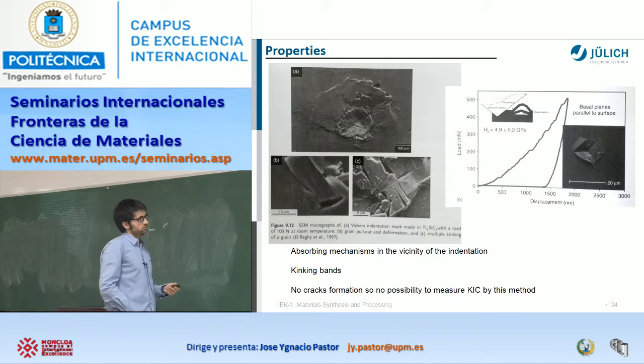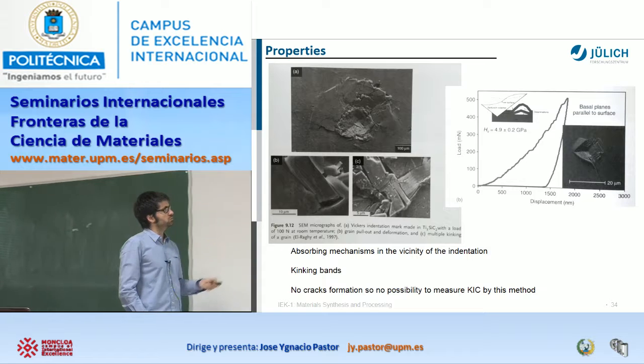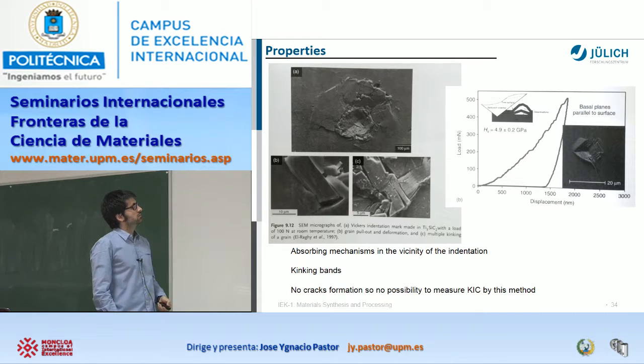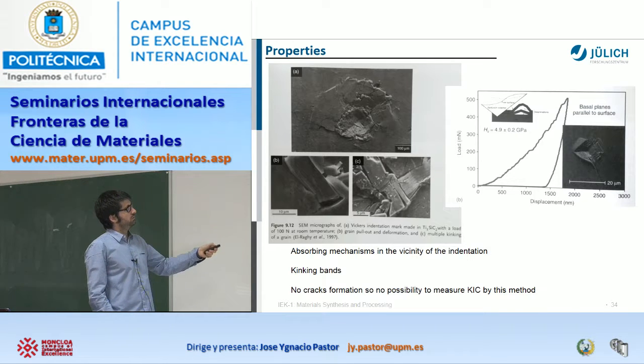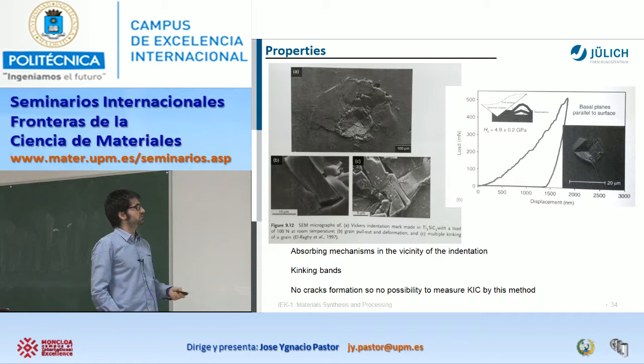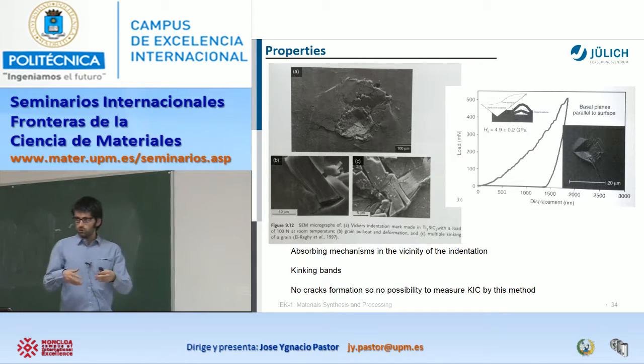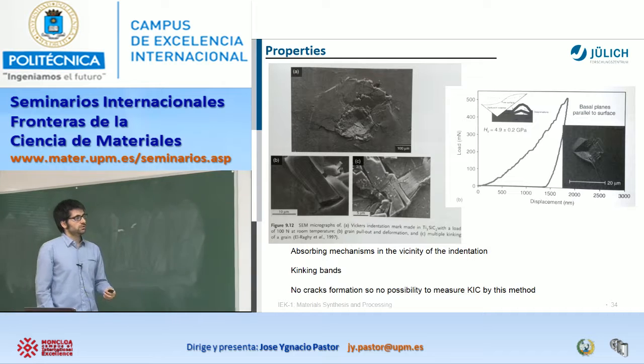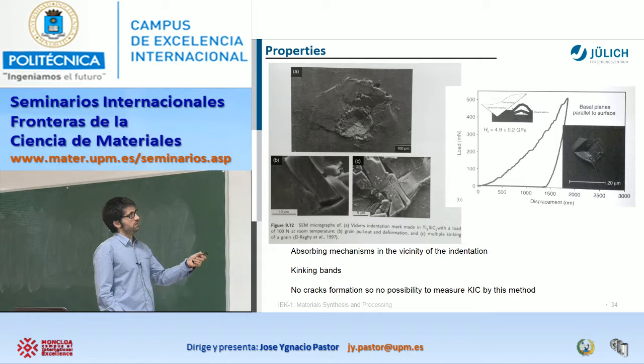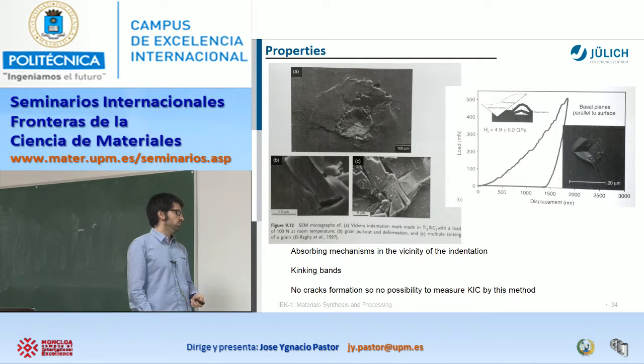But these MAX phases are totally different. When you indent with your bigger tip, there is an area that is obviously deformed, but then there are no cracks, because what you produce when you introduce your tip is some delamination and some kink bands surrounding it, like here, and then they absorb all the energy, okay? You absorb the energy of the indentation, and then there are no cracks. Then the material can really survive.